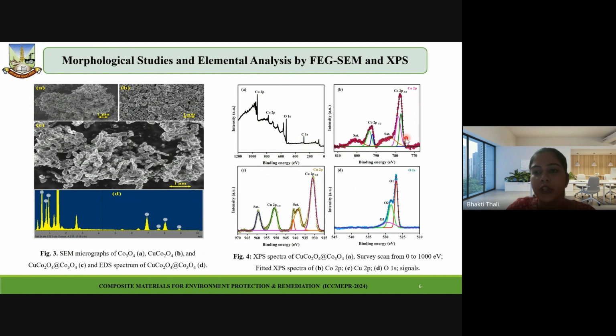Cobalt 2p is deconvoluted into two peaks at 778 electron volt and 792 electron volt, corresponding to the Co3+ oxidation state, and the other two peaks are for the Co2+ oxidation state. There is also the presence of two satellite peaks for cobalt 2p.